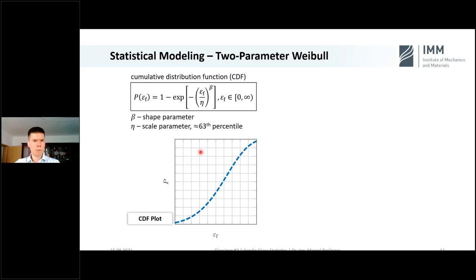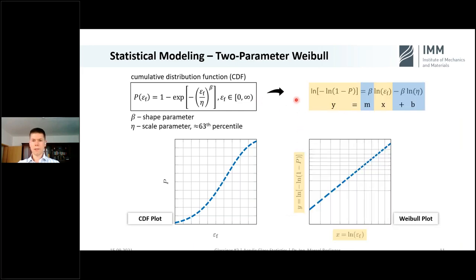Now, before we saw the two-parameter Weibull plot as a linear line. That is performed by transformation of the axis, which I want to show in the following. We can solve this equation, and then you can guess. We can take this side as the y, and here the ln epsilon as our x, and such we do get an expression for a linear line. But you can see in both plots, the grid is the same, on the same limits. In this diagram, we have scaling in our space. So we did perform our function fitting in this area here.